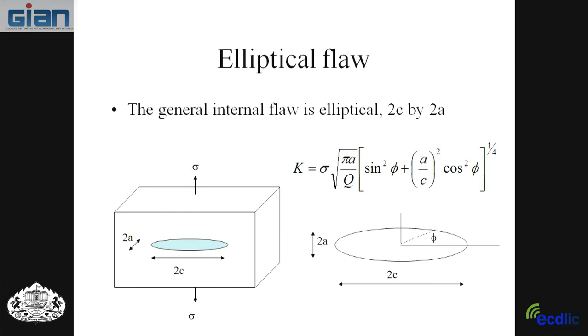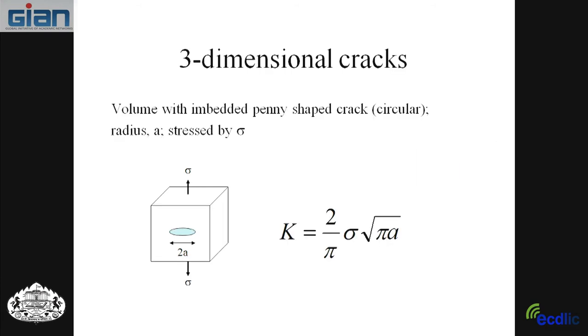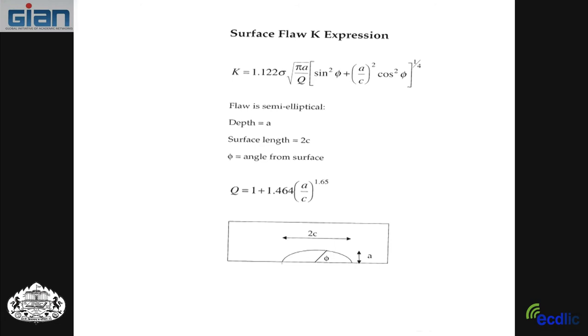In an elliptical crack, when you are closer to the center, you get higher K's. It's just a mechanics thing. I don't know physically you can say anything else. But the closer you get to the center, as you go from the distance out here and get closer and closer to the center, the K increases. It keeps going up and up. So a lot of times with an elliptical crack, or a semi-elliptical crack, sorry, people just worry about that point right there, the K right there, because it is the highest K.